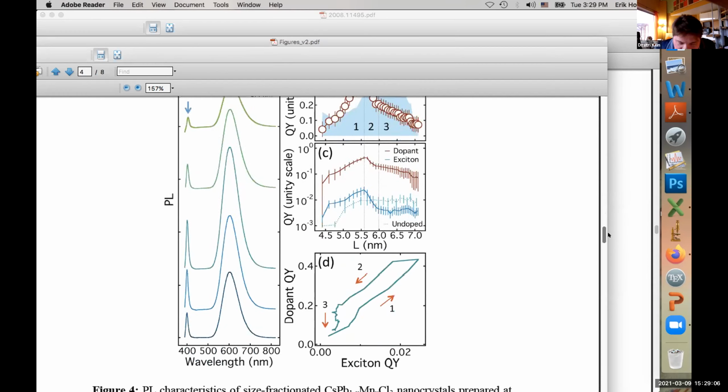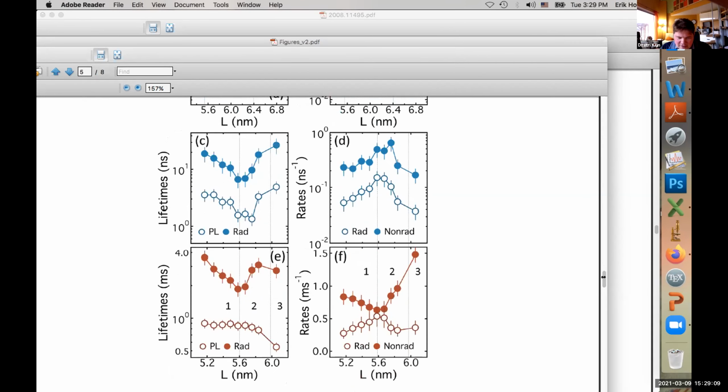Right. I feel the smell that there is an effect. If the concentration of dopants is low, then, as in considerations of impurities like NV centers in diamond, the impurity looks almost like an atom in vacuum, isolated. It doesn't have resonance states to transfer energy. If we increase the concentration, then it will be a band of these impurities, and they have transitions between each other that will add additional non-radiative transitions.